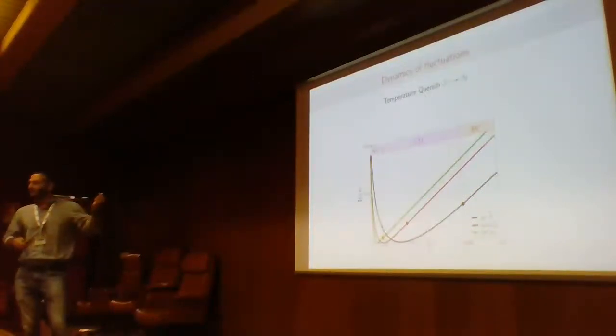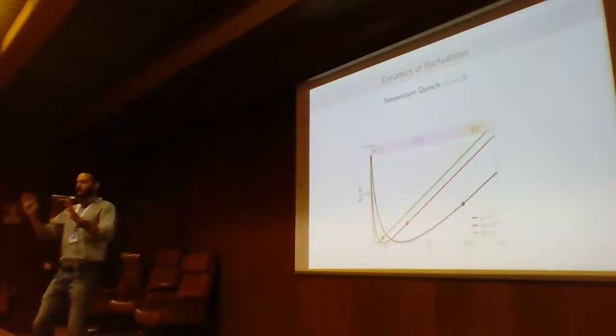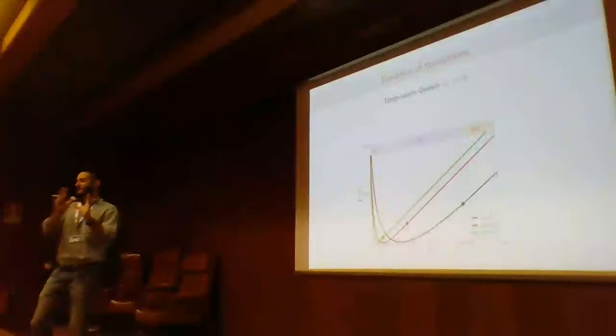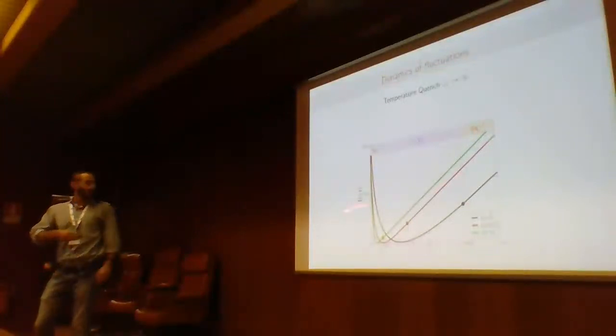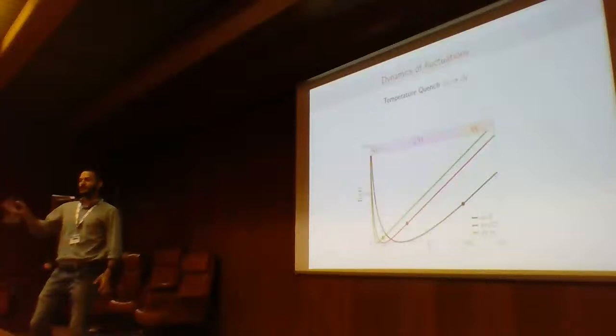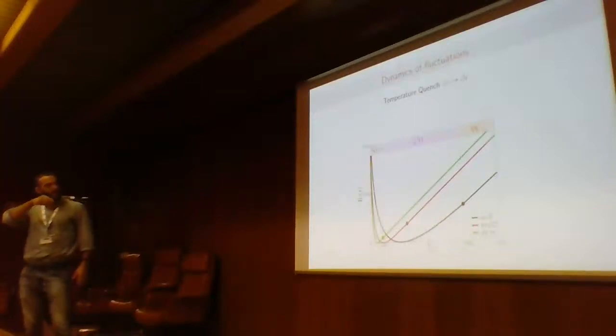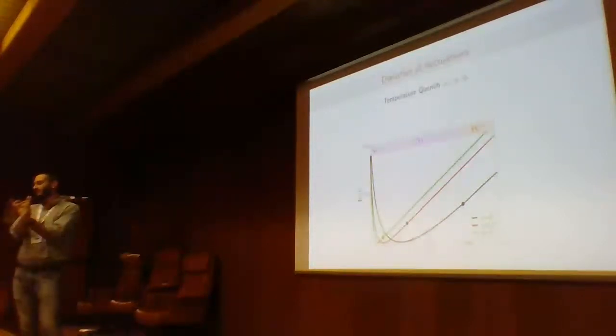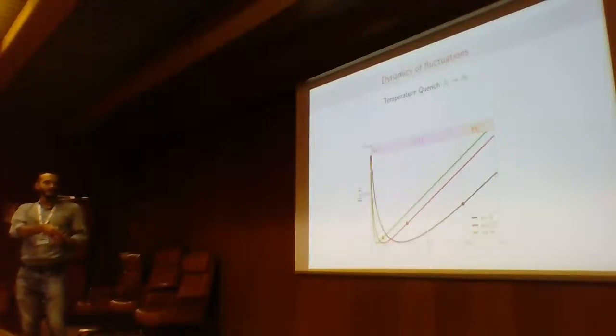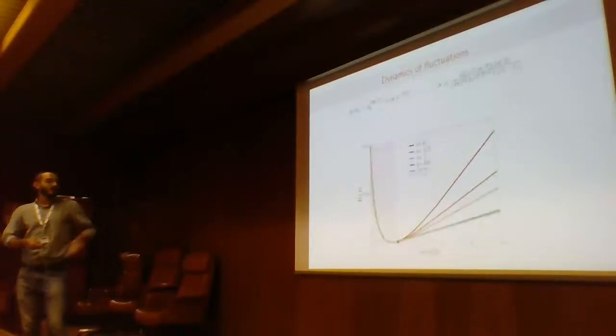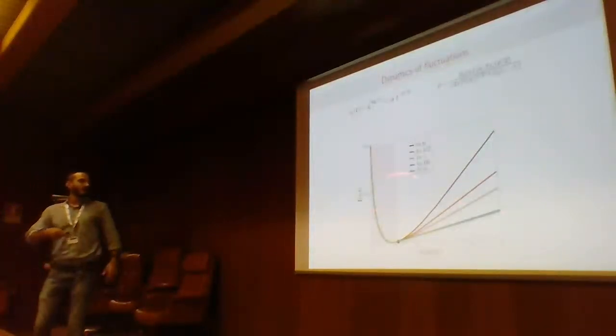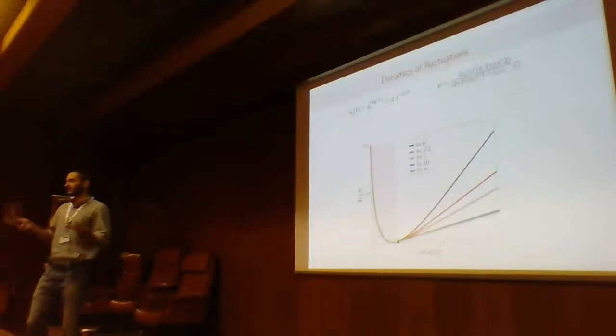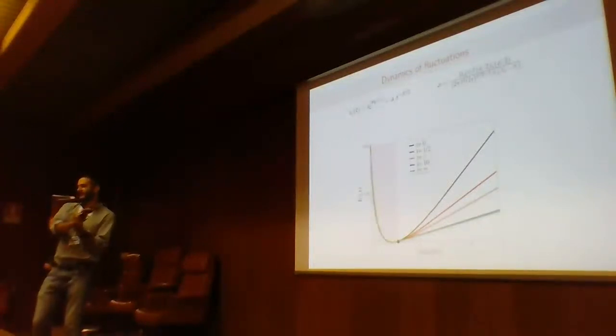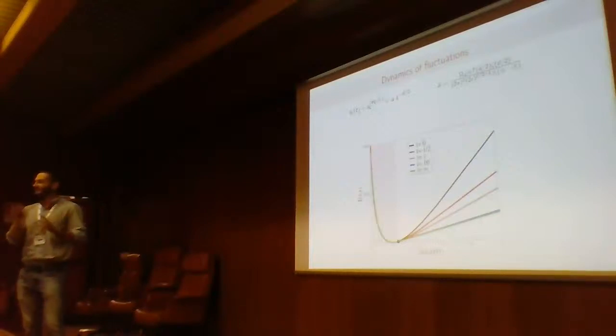And to have more insight on why this can be interesting, I have to mention that at equilibrium, if I prepare the system at different temperatures, and plot the rate function against S over the average value, which is related to the temperature, I'm not showing you this, but trust me, all these rate functions at different temperatures collapse on a master curve. So in this case, this is what happens. This brown part is where fluctuations never condense. And so they behave like they adiabatically relax to their final state. So it's an equilibrium-like behavior.